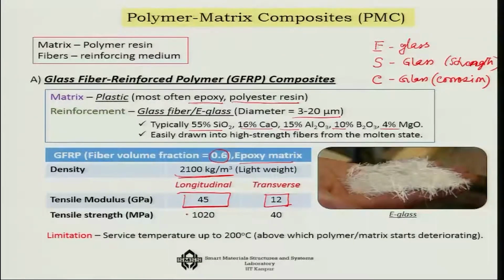Then the tensile strength is about 1020 MPa in the longitudinal direction and about 40 MPa in the transverse direction. The only limitation, so structurally it is quite good. In fact, wherever steel with a moderately loaded element is needed, or aluminum, you can very safely use glass fiber reinforced plastic today. If you need slightly more strength, you can go for S glasses, etc. But the limitation is that the service temperature is up to 200 degrees centigrade. It should not go beyond that. If it does, then the flow will start, or the degradation of the matrix will start. So this is the limitation, temperature wise.